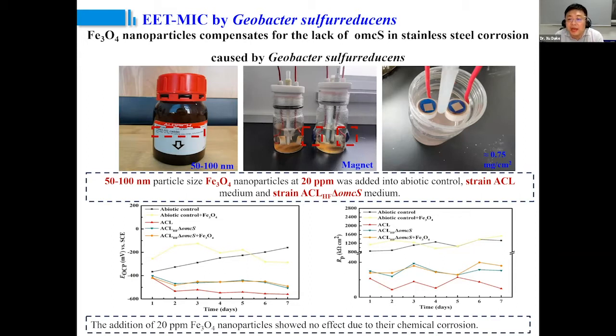The idea we have is we follow some research in EET, and the paper was recently published. So we bought iron oxide in size like 50 to 100 nanometers. This is the initial work, and we have a series of work on nanoparticles, so this is just preliminary data without publication. We first make the nanoparticles attach on the electrode, and then we test the corrosivity.